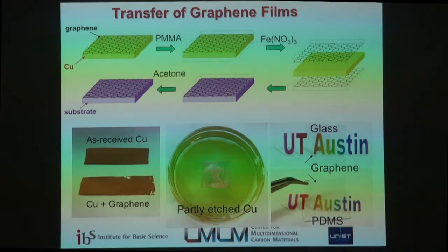So this sort of approach has been something that many groups around the world have used, but if you're not aware of it, please be aware that there's been a lot of progress on other sorts of transfer methods where you don't have to dissolve the metal, you can use it over and over, essentially ad infinitum, and dry transfer methods where you're left with less and less residue. For our center goals, this is incredibly important. We're putting some emphasis on trying to transfer graphene from its growth substrate so it has no residue. That's very challenging because if you just expose a sample to ambient, adventitious carbon or hydrocarbons adsorb on the surface.